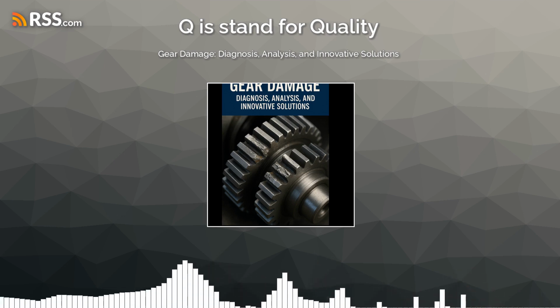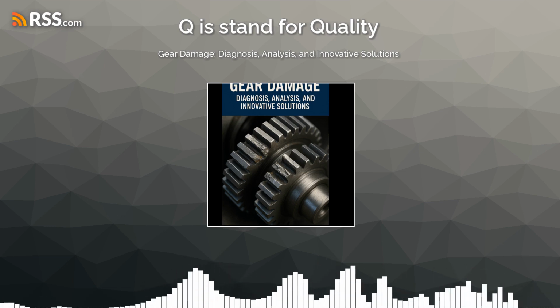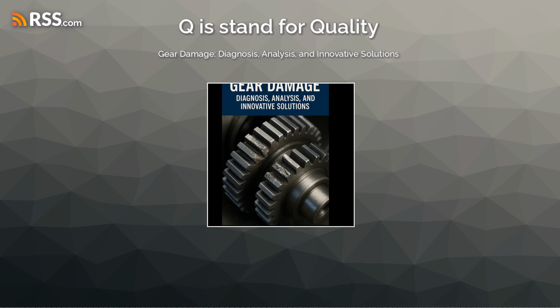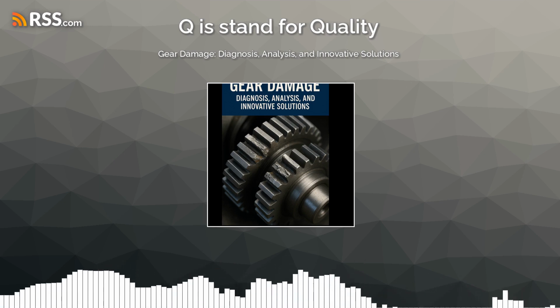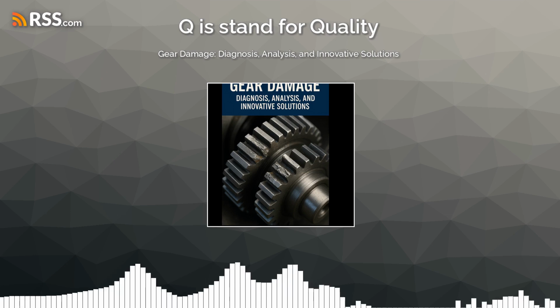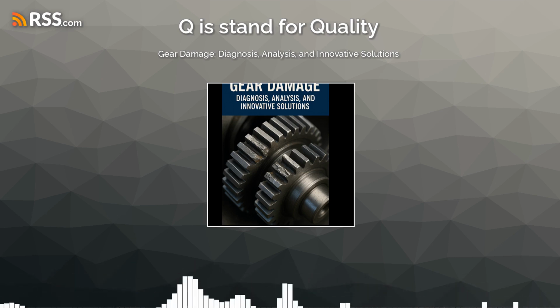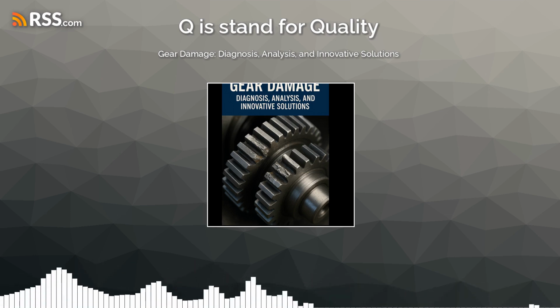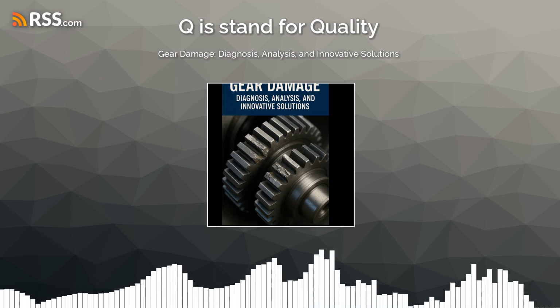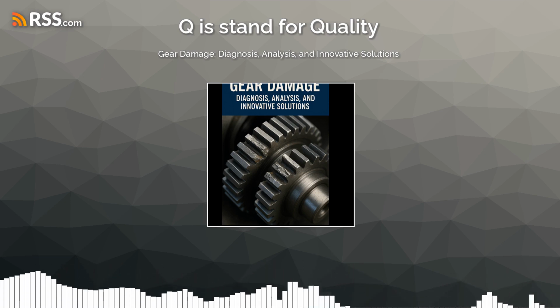Then you go deeper with microscopic analysis. This sounds like where the real clues lie. What tools are used here? This is where we get down to the nitty-gritty. First, usually a stereo microscope, then the powerhouse, scanning electron microscopy, or SEM. With a stereo microscope, you look closely at the fracture surface edges, the color.